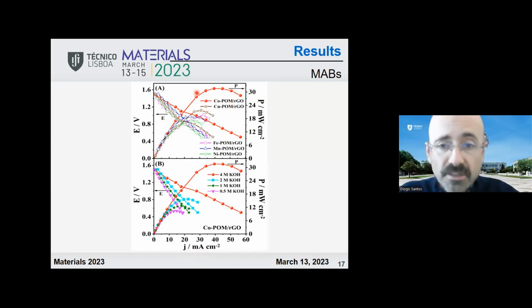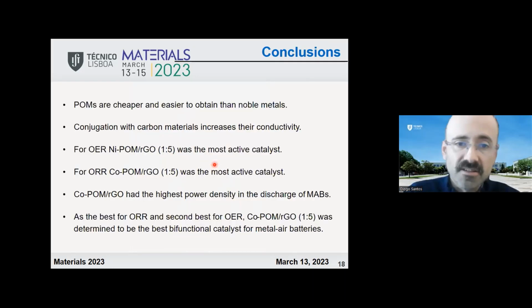So the cobalt POM had the higher power density during the discharge. We managed to attain 30 milliwatts per square centimeter during the battery discharge. So these were very interesting results. And besides that, we also tested with different electrolyte compositions. And it showed us that the higher power densities were obtained also with the concentration of electrolyte of 4 molar KOH. So with the increase of electrolyte concentration, power densities also increased.